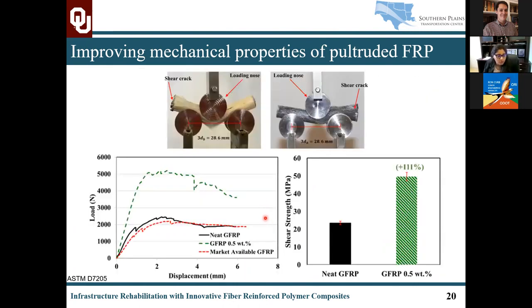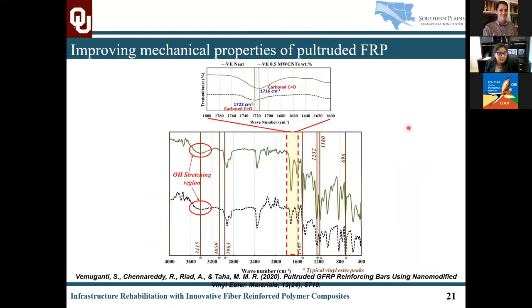With the main focus, which was the shear strength, huge improvements were seen due to this nanomodification. About 110% improvement in the shear strength was seen with the resin modified with carbon nanotubes versus resin not modified with carbon nanotubes. It has seen a huge improvement even with market available GFRP. And it was a very crucial thing to observe that these nanomodifications can bring in a lot of enhancements.